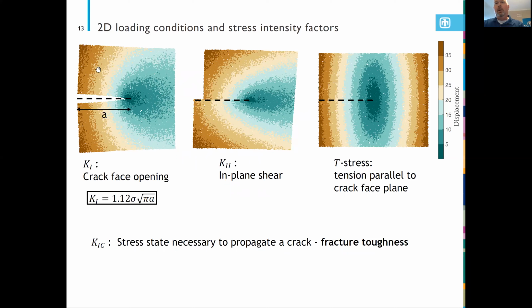Ultimately, I just took a series of points in a box and I applied a given K1 loading. This is an opening loading, so you're pulling the material open. The original crack face plane is the dashed line here. So that's an opening loading. K2 is an in-plane shear where you have the top material being forced to the right-hand side and the bottom of the material being forced to the left-hand side. And T stress is a tension in the direction parallel to the crack face plane.